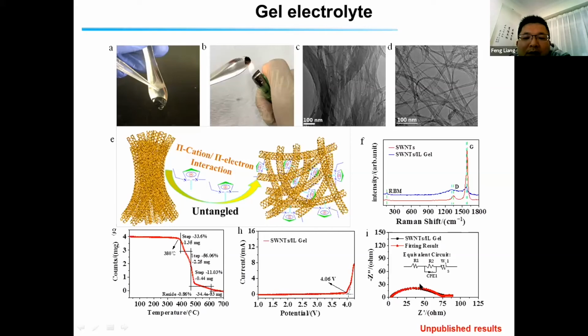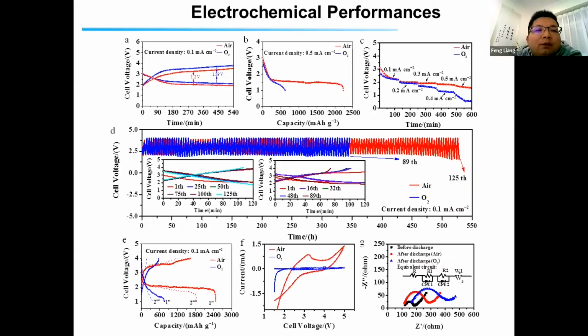Also, we measured the ionic conductivity. So it's about 1.3 multiplied by 10 to the power of -3 Siemens per centimeter. So it's very high. And then we used this gel cathode in the quasi-solid-state sodium-air battery and the solid sodium oxygen battery. So this is the electrochemical performance.